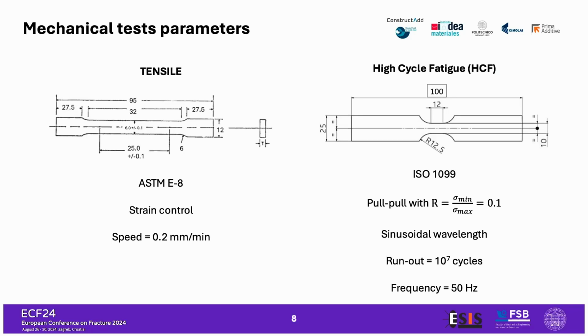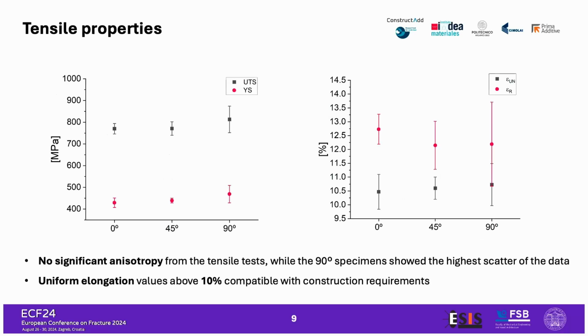We performed tensile and high cycle fatigue tests, in particular tensile tests in strain control at 0.2 millimeters per minute, while the fatigue tests were in pull-pull condition with a stress ratio of 0.1, setting the runout at 10^7 cycles and testing with a frequency of 50 Hertz. So let's go to the results from the mechanical tests.